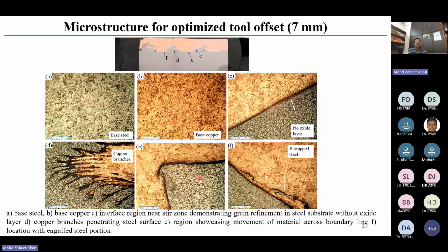So two important things can be seen from this. One, there is mechanical interlocking, there is metallurgical bonding that has taken place, and there is grain refinement that has taken place in the substrate material. So if the grain of the substrate material have become finer, that means the mechanical property of the substrate has also improved a little.